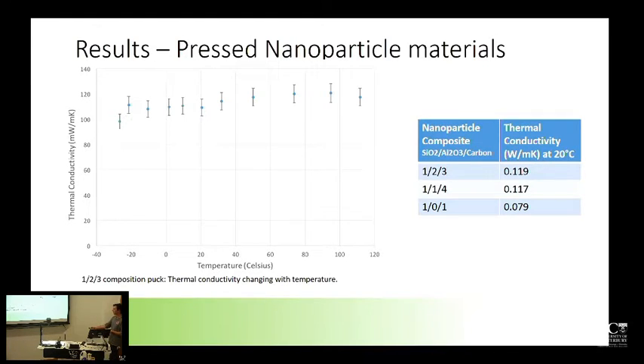So this one here is for a 1, 2, 3, so one silica, two alumina, three carbon weight ratio puck. According to literature, they found this was like 8 milliwatts per meter Kelvin at room temperature, ambient pressure. The way that they measured it in literature, though, was they used a laser flash calorimeter, I believe. So they took a puck of material, had an infrared laser pulse on one side, waited for the pulse to emerge on the other side, and then measured the intensity and the time delay, and then converted that into thermal diffusivity and thermal conductivity.